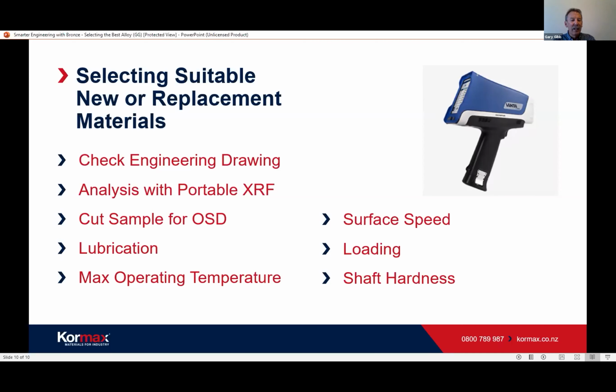The other thing we look at is the maximum operating temperature. Typically, your bronzes that we've discussed today, the tin bronzes, the gunmetals and that, up to about 220-230 degrees Celsius. The aluminium bronzes, 260-300 degrees.